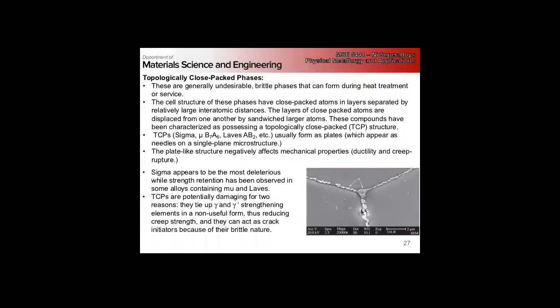The other generally unwanted phase are these topologically close packed structures - brittle phases that form during heat treatment or in service. Basically we have close packed atoms in layers, and then we have things in between that tend to separate these close packed layers, so we have like a sandwich structure.